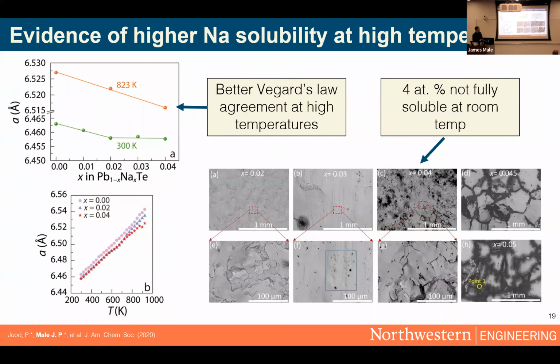Of course, the first place we looked was high temperature solubility. We found through X-ray diffraction experiments that the lattice parameters demonstrate good solubility up to about 4 atomic percent at high temperatures. However, we don't see solubility above 2 atomic percent at room temperature. So this basically suggests sodium is diffusing more into the matrix at high temperature, and we're not able to freeze it in well when we bring it back down to room temp.